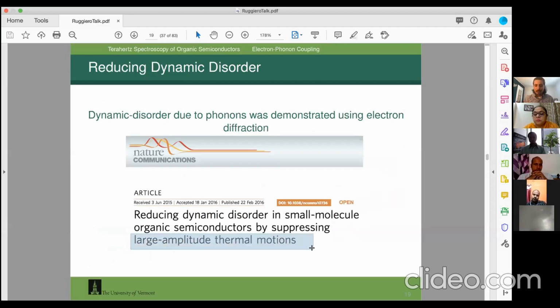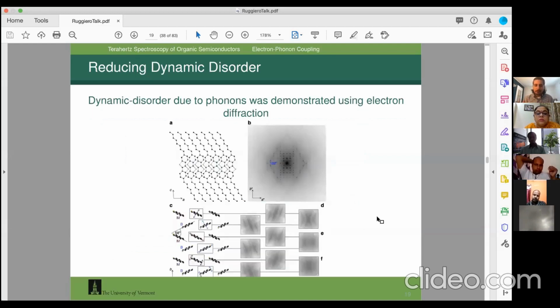This large amplitude thermal motions, I see that and I just change it to terahertz motions because they're the same exact thing. What they originally did before they met me, to show that there were these large amplitude motions, was take a series of organic semiconductor crystals and do electron diffraction of thin films. They analyzed the streaking in the diffraction dots, in the diffraction peaks, and that streaking is a measure of how much motion there is along that direction.